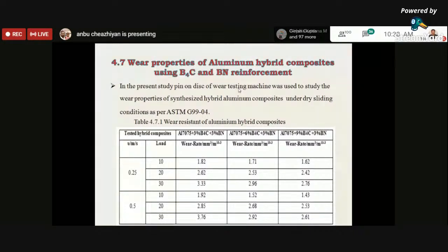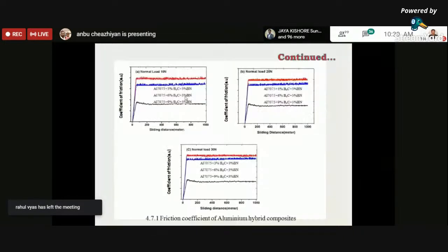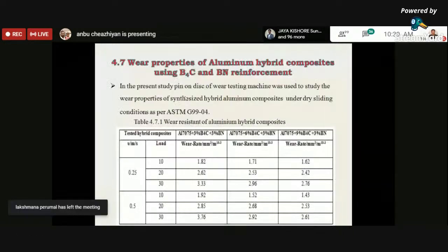So it is observed that the composites, for all the combinations, by varying speed and varying loads, have significantly decreased the wear rate. This is due to the fact that an increase in load tends to increase the wear of synthesized composites, and hence the wear rate also increases. Due to the presence of harder reinforcement, the motion of dislocations is restricted, and hence the wear rates significantly decrease when compared to the monolithic material. And so this is the friction coefficient.